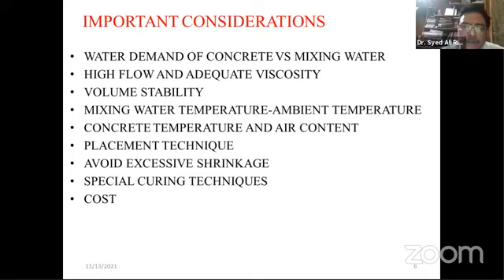Now the question may arise, what can be the problems if the mixing water content is less than the water demand of the system? Then we will have volume stability issues. Shrinkage will be a very big problem. And if you use water more than the demand of the system, then you may invite segregation, or if the viscosity is adequate, you might lose strength, because strength depends upon the mixing water content. So therefore, in my opinion, it is the first and very important point to determine the water demand of concrete. Okay, then you should have a high flow and adequate viscosity, because otherwise you will not avoid segregation and you will not be able to produce self-consolidating concrete.